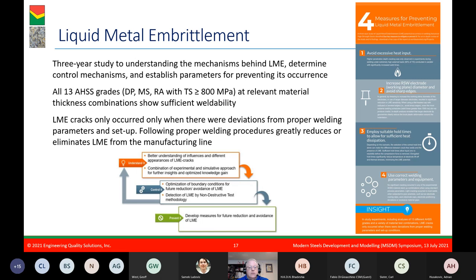Also on this site is great technical information about projects done under the auspices of World Auto Steel. For example, a 3-year study on liquid metal embrittlement showed that the risk of LME cracking greatly diminishes simply by diligently adhering to proper weld procedures like minimizing heat input, using sufficient hold times to allow zinc solidification, and proper electrode alignment. Partners on this study included Paderborn University in Germany, the Institut de Soudure in France, and Fraunhofer Institute in Germany. The results from this detailed study are available as a free download, and of course, pertinent articles within the joining guidelines are linked to the study.